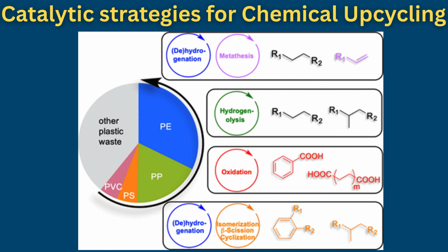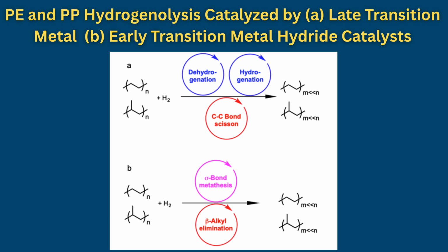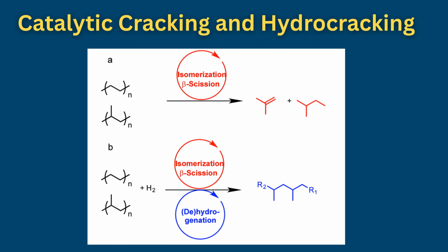Hydrogenolysis. Hydrogenolysis involves metal-catalyzed C-C bond cleavage in the presence of H2. It is operationally straightforward and can proceed below 300 degrees Celsius. Products include saturated hydrocarbons suitable for lubricants, waxes, solvents, and fuels, jet fuel, diesel, gasoline, naphtha. However, terminal bond cleavage produces methane, which lacks added value. Additionally, hydrogenolysis relies on energy-intensive H2, typically generated via methane steam reforming.